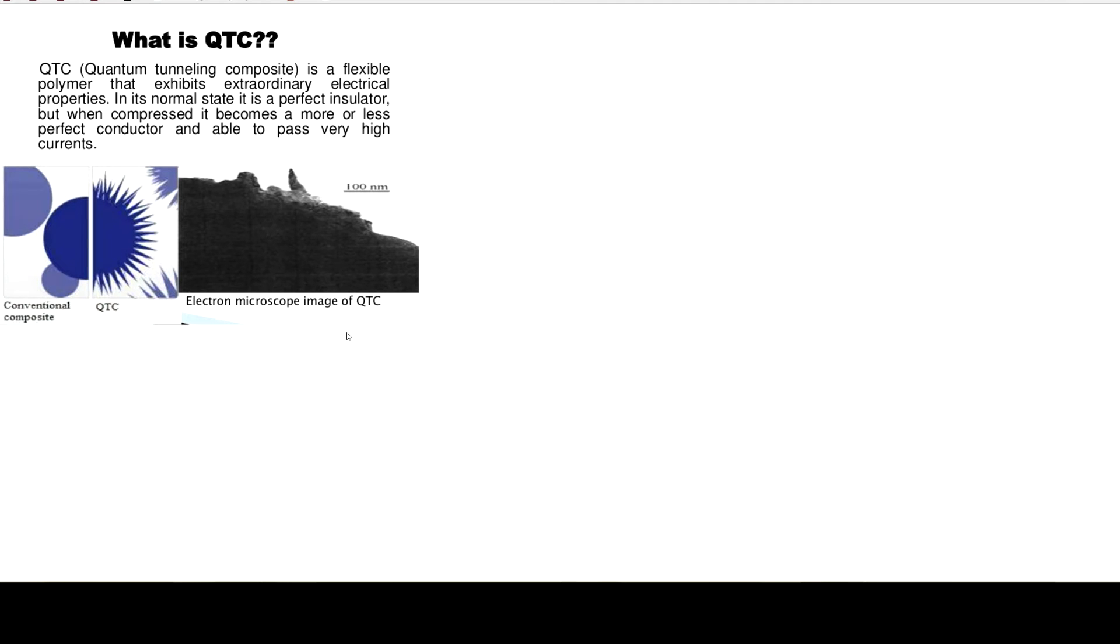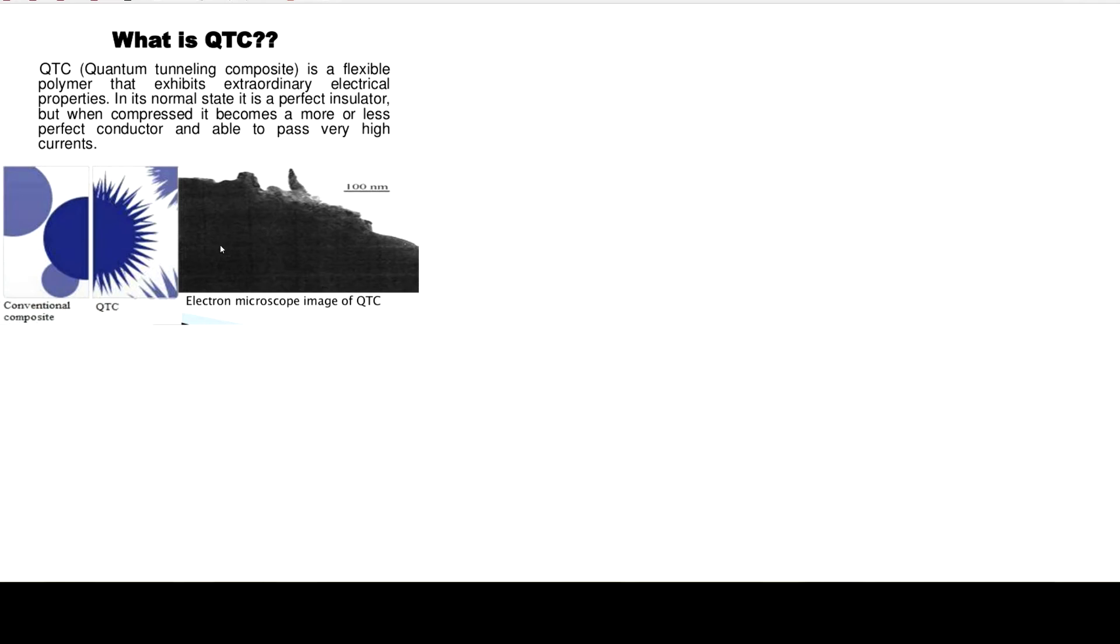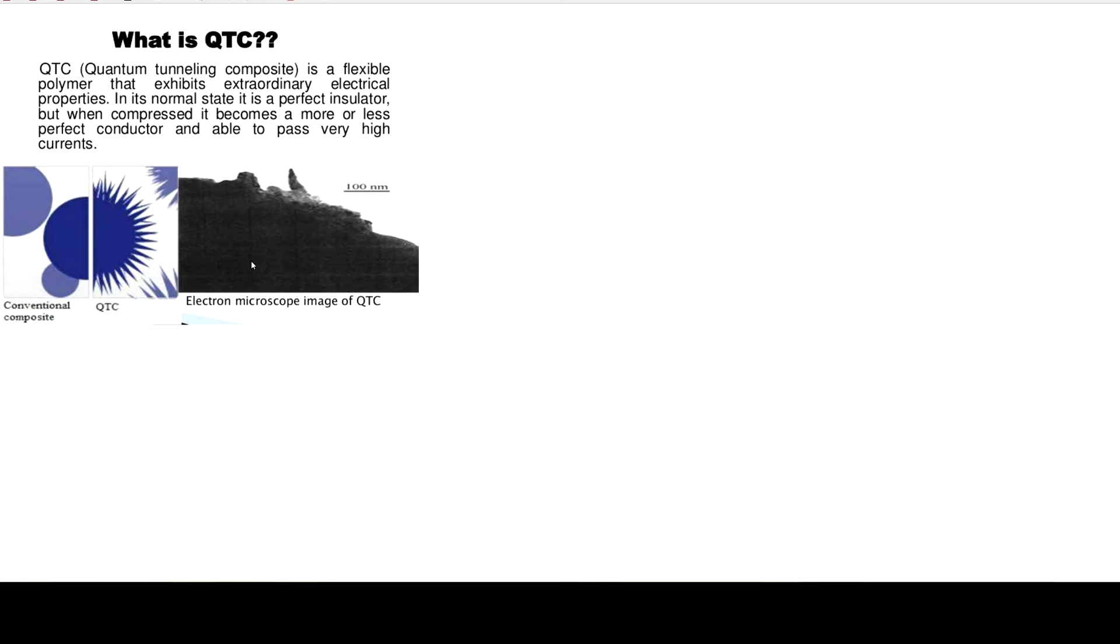So if you look at how this pertains to quantum tunneling composites, what we have here - the whole thing about the quantum tunneling composite, it is just a plastic. It's a piece of, I think, polyurethane or something like that. But there are these very small particles, tiny nanoscale particles, very spiky - I think it's nickel. These spikes are what enables this quantum tunneling effect. Because normally, if you have a polymer material and you put in metal to improve its heat conduction or electrical conduction, these particles are essentially round when they go in. So if they get closer together, you don't have that much surface area that comes close to each other.